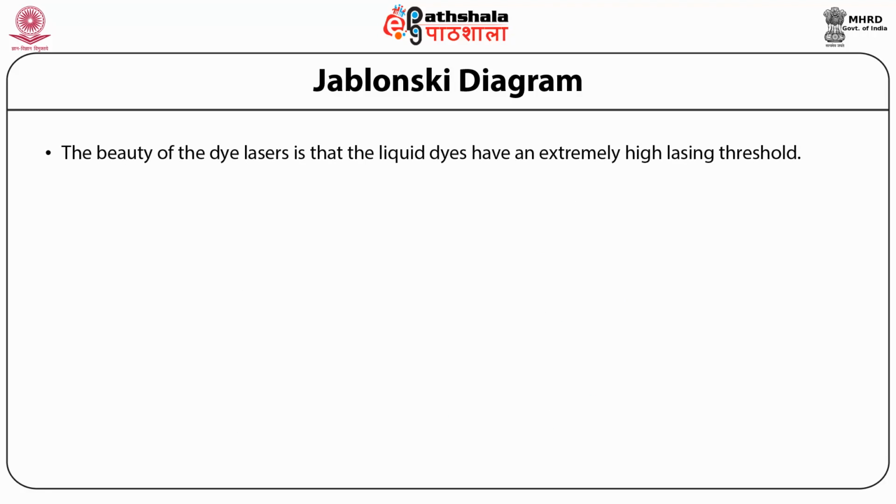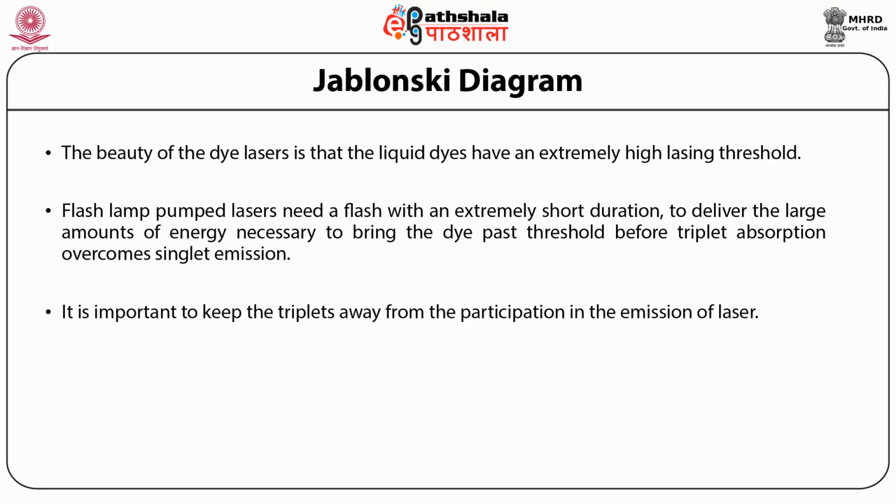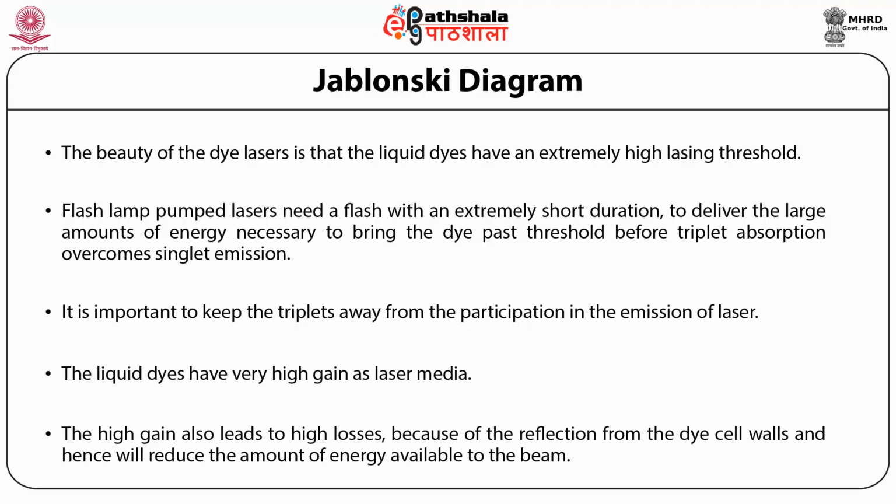The beauty of the dye laser is that the liquid dyes have an extremely high lasing threshold, and flash lamp pumped lasers need a flash with an extremely short duration to deliver the large amounts of energy necessary to bring the dye past threshold before triplet absorption overcomes singlet emission. It is important to keep the triplets away from participation in the emission of the laser. The liquid dyes have very high gain as laser media. The high gain also leads to high losses because of the reflection from the dye cell walls and hence will reduce the amount of energy available to the beam.